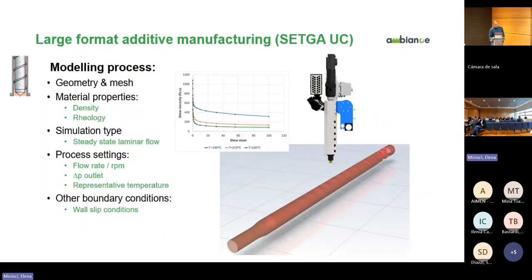So let's go for the first one. We have made a simplified model of the inside part of the extruder, everything that is inside the barrel and the screw. The material properties for this type of simulation are experimental rheological curves that have been measured by AIMEN. Here we are simulating the rotation of the screw inside the barrel at a steady state regime. So the flow is laminar. And here we involve several boundary conditions. First of all, the coupling of flow rate and rotation speed. This is a very important relation in extrusion, so we impose one to obtain the other.